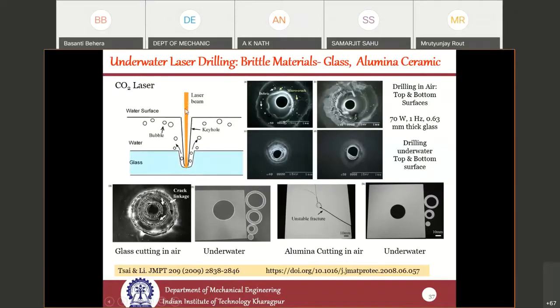With this setup, the laser beam penetrates in and reaches the glass surface. On the glass surface also, the CO2 laser gets very readily absorbed, and with that you can do the processing. Compared to air, where it generates a lot of thermal cracks when doing laser cutting, in the case of water, underwater, with the help of a CO2 laser, you can generate very good quality cutting without any cracks. Here, the alumina ceramic has been cut in air.